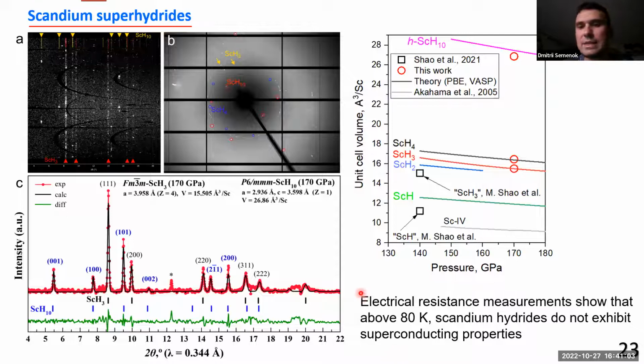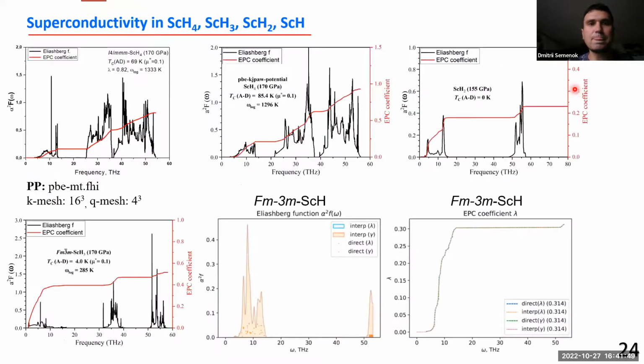So there are no problems with determining the volume of scandium hydrides. But in fact, the electrical resistance measurements showed that above 80 Kelvin scandium hydrides do not exhibit superconducting properties. Right now, I cannot show the dependence of electrical resistance on temperature, but I think I should get this data within maybe a few days, maybe one week. But we detected that above 80 Kelvin we cannot see any signs of superconducting transition, and the behavior is like in a normal metal. So it means that this scandium H10 is probably also a molecular hydride, and we need to compress it more and reach 250 or maybe 300 GPa to convert it to a metallic superconductor with an atomic hydrogen sublattice.